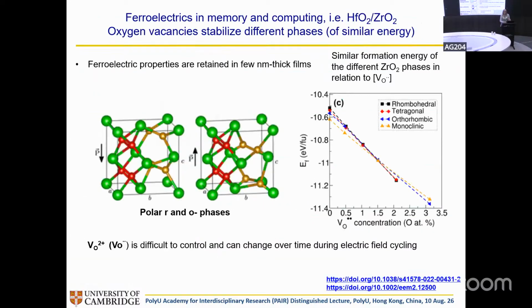Now let's look at the ferroelectric ones as well. Same kinds of problems. Very interesting ferroelectrics are hafnia and zirconia in recent years. These have been studied very widely. And here, again, we have oxygen vacancies in these materials. So you just lose some oxygen atoms that come out, leave these vacancies. And the switching occurs by some slight tweaking of the structure when you apply the voltage across it, and you see the polarization moves up and down as you change that structure.